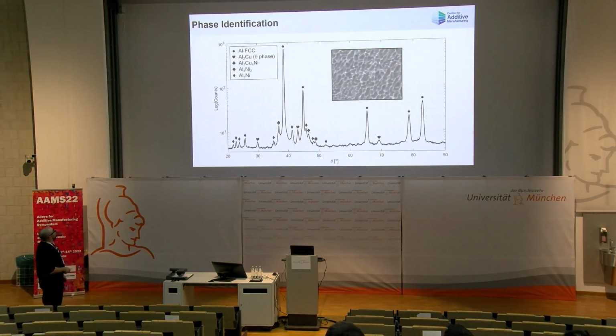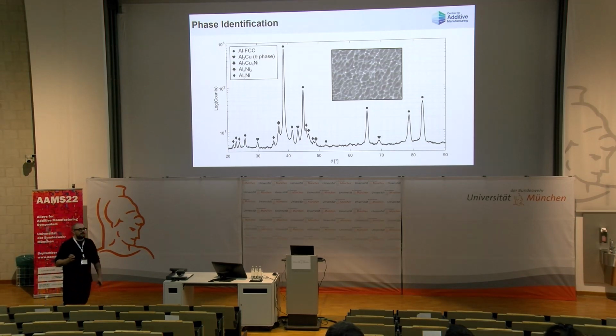Of course, we wanted to double check the phases, and these are the same phases that we find in the remelted buttons. So this is quite a complex alloy. We can see the FCC, the famous theta phase, but also two different aluminium-nickel compounds and a ternary compound. All of these can be somehow spotted here with different intensities of the white phases, but this needs more analysis to be precise.